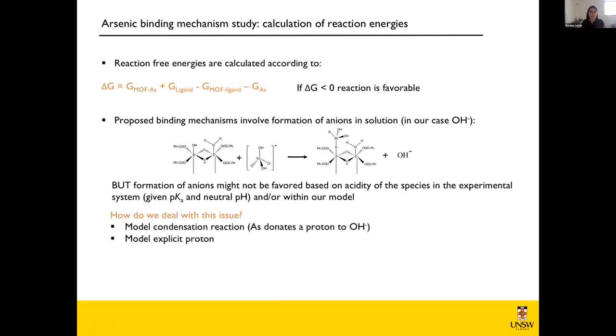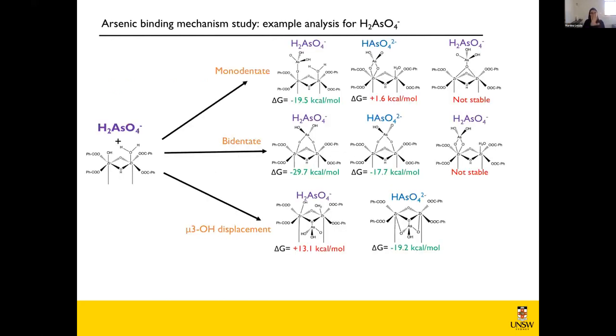We used two different options here, which have different advantages and disadvantages that I don't have time to discuss. But essentially, we tried to protonate the hydroxide either by taking a proton from the arsenic, forcing it to get deprotonated in order to bind, and then also we modeled an explicit proton. With this, I'll show you the complete analysis that we did for dihydrogen arsenate, and all the binding modes we've looked at so far.